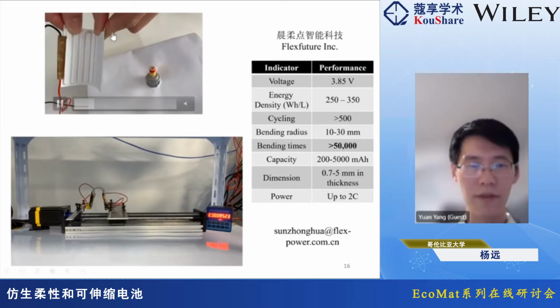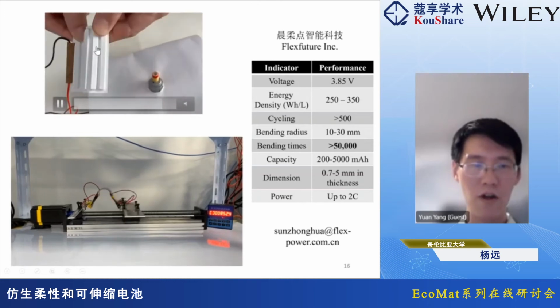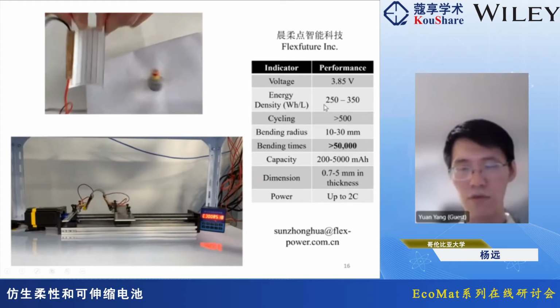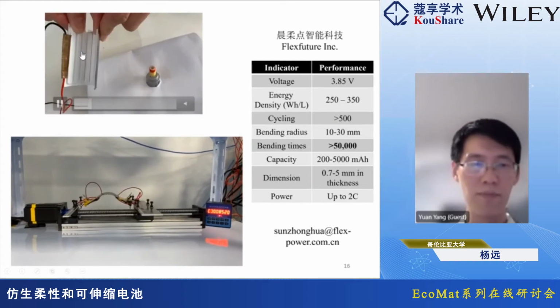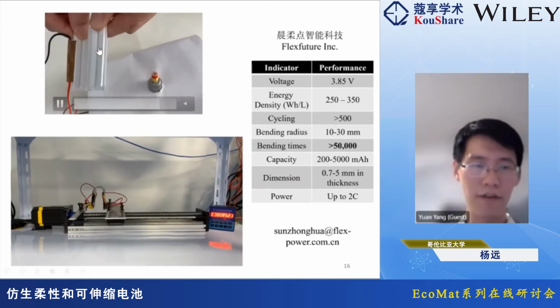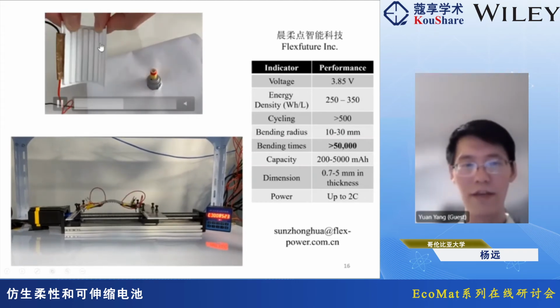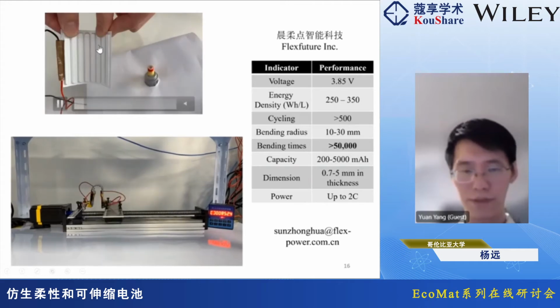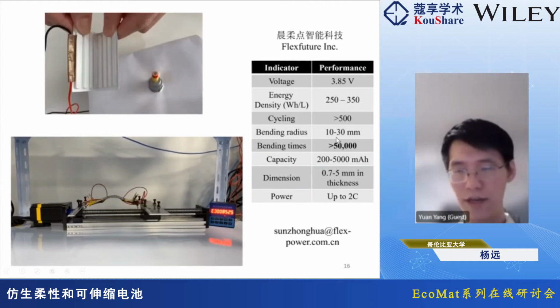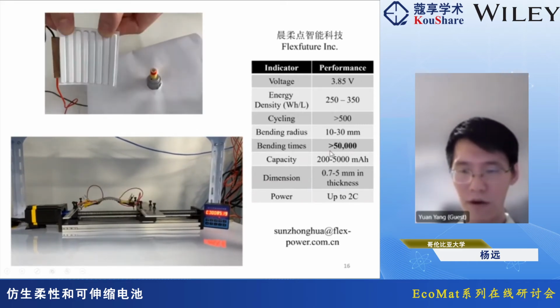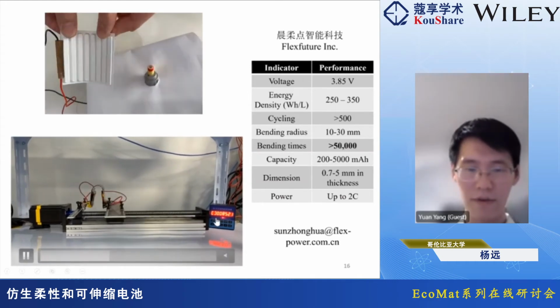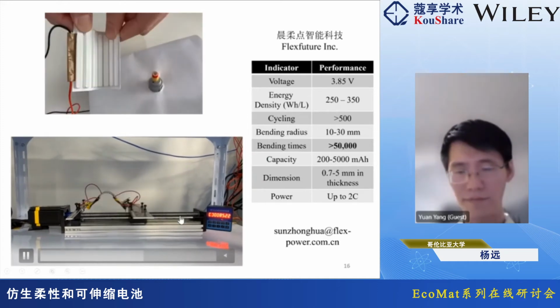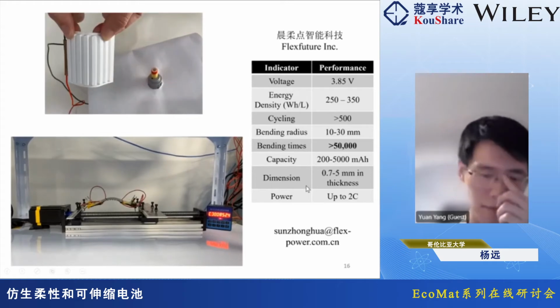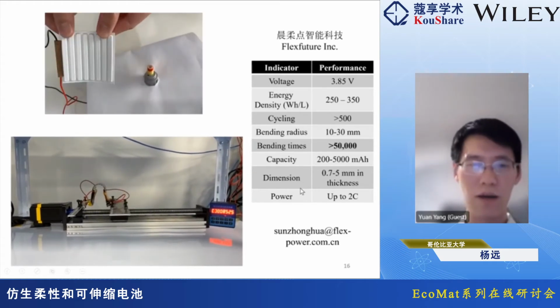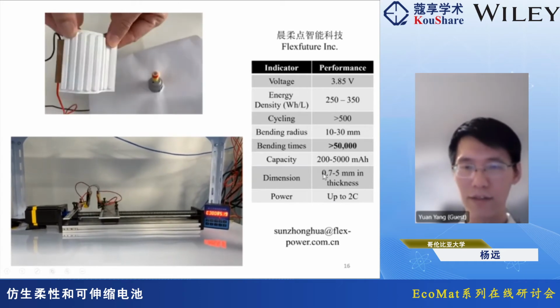In this cell configuration, if you take even all the volume between the different segments into account, the energy density is between 250 and 350 watt-hours per liter, and if you just consider the volume of the segments, the energy density can reach about 550 watt-hours per liter. That's similar to standard lithium-ion batteries. We can also reach a bending radius of 10 to 30 millimeters and bending times over 50,000. And this is a test; from the number here, you can see it's 8,000 times. The dimension and capacity can be changed based upon demand. The company is also hiring battery scientists. If you are interested, feel free to contact the company. It's based in Shenzhen.